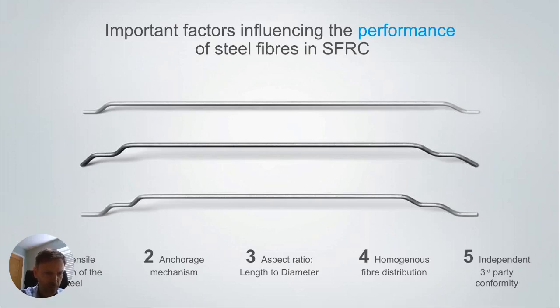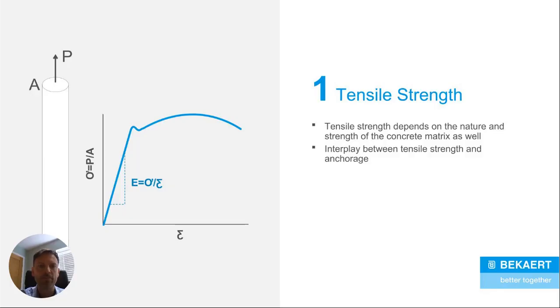The first one is the tensile wire, the strength of the wire, okay? Most of our steel fibres use a tensile grade of wire of anything from 1100 to 2300 newtons per square millimetre, so at least twice that of traditional mesh. If these steel fibres with this shape were made from 500 Newton grade wire, just like mesh or rebar, then they would fail in the concrete.